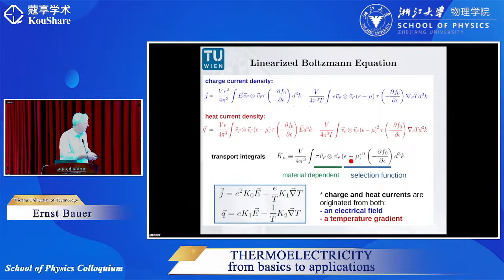So as you can see here, this term here on the far right part of this transport integral is called selection function. It's this energy difference and the energy derivative of the Fermi-Dirac distribution function. This seems to be material independent, so it's only temperature dependent. And the left term here clearly is a material dependent quantity because the velocity of the charge carriers is dependent on which material or which Fermi temperature the material has, and clearly the relaxation time depends on pretty much the same processes.